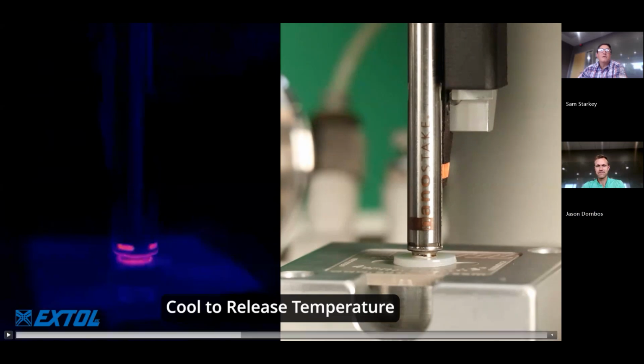Right. Yeah. Is there a way to increase the cycle time? If I have a shorter machine cycle time, the tip needs time to reach the temp. Is there a way to set different power levels for the tips? Yes. So the tip goes from ambient temperature to operating temperature, whatever that is, whether it's 500 degrees Fahrenheit, 600 degrees, in like seconds. In fact, in this video, the tip starts out of frame above the shot, and by the time it's in frame getting to the plastic part, it's almost all the way to temperature already. And then we cool it back down to ambient temperature every single cycle. So it's like a second or two to cycle temperature on these things.